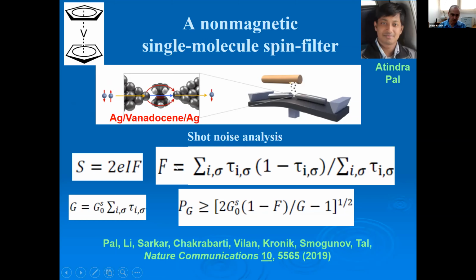In a shot noise analysis, one can show that there is a noise coming from the individual motion of electrons. It is related to a term known as the Fano factor F. The Fano factor is related to the partial transmission or reflection through each transmission channel, which also depends on spin in this form. And then, of course, the conductance is the general summation over all of the transmission channels. And one can show that the probability for a spin polarization is related to these two factors. It has to be greater or equal than some combination of the Fano factor and the overall conductance.